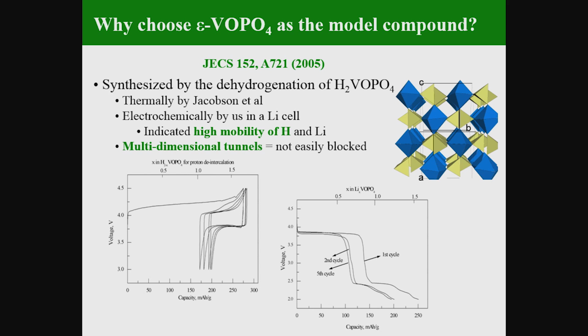So at that time, here is the first cycle, about 4 volts, and the second redox couple is about 2.5 volts. And you see in the first discharge about 250, and it's down to about 200 in the second one. So that was some indication that there was something interesting here. Valence was looking at a fluoride analog of this at that time. We were discouraged from working on this further by our sponsors. We don't like vanadium. So we stopped for about 5 years until they said, why aren't you working on vanadium? So we went back to it.